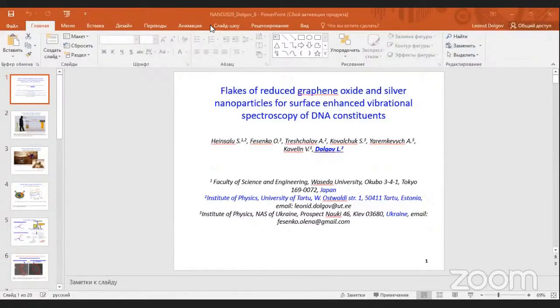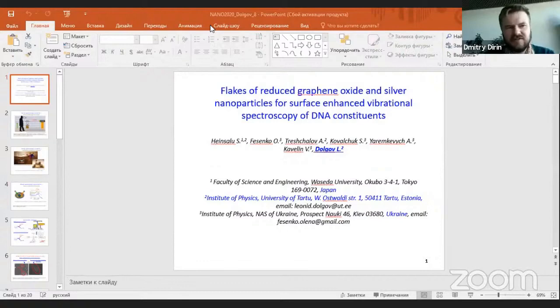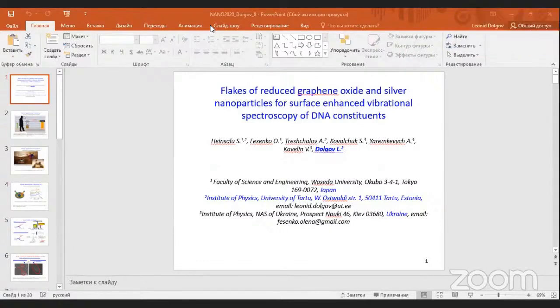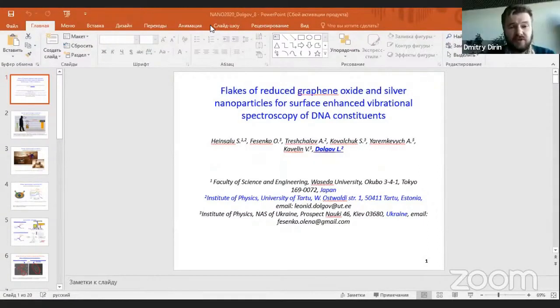Thank you. And one more question. Have you some data about the influence of the chemical composition of the metals? Again, if I understand right, you're asking how the chemical composition of the materials which you stabilize affects optical properties. So at the moment, the whole field is limited to only several compounds. It has to be lead halide perovskite, so lead, but only with chloride, bromide, and iodide. And as the A cation, we are limited to cesium, methylammonium, and formamidinium. All those 9 compounds are considered for many different applications, but in reality methylammonium-based materials are intrinsically unstable, and cesium and formamidinium are more stable.